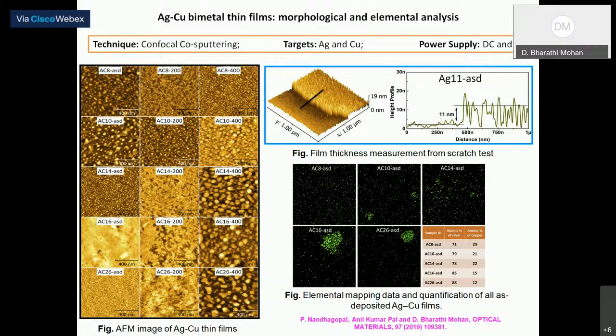And the atomic percentage of silver and copper has been investigated with the help of EDX mapping, and we found that as you increase the DC voltage, the copper content decreases from 29% to 12%. The AFM image shows the as-deposited film as well as the annealed film. As you increase the annealing temperature, the particle size and shape become more homogeneous, and when you decrease the copper content, the particle size becomes bigger and bigger, and the roughness also increases. The film thickness is calculated using the AFM technique, just by scratching some portion of the film and scanning along this direction, and from the step size we can measure the thickness of the film.